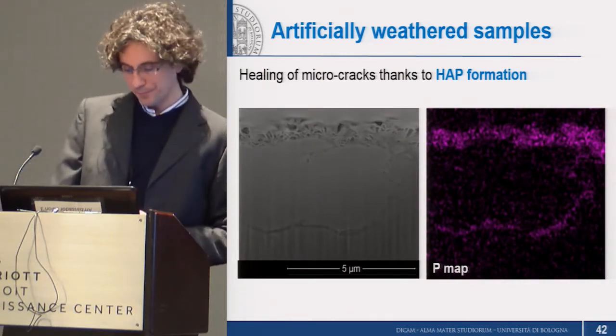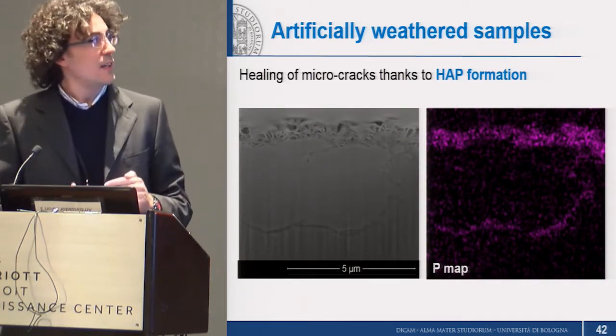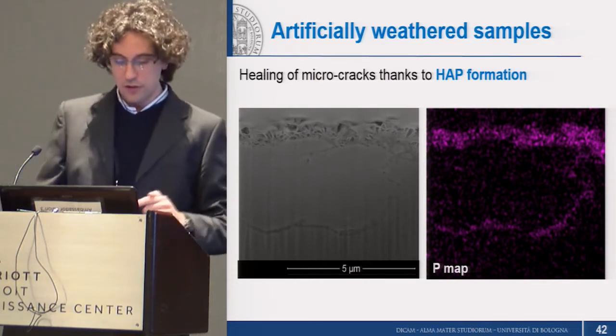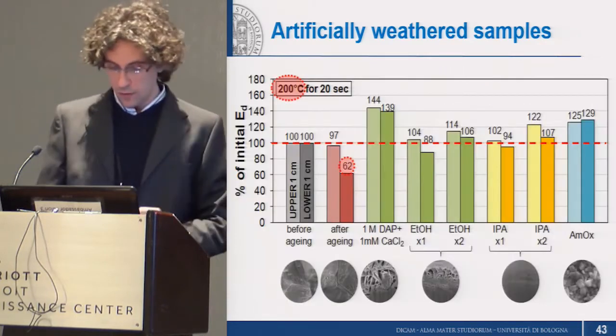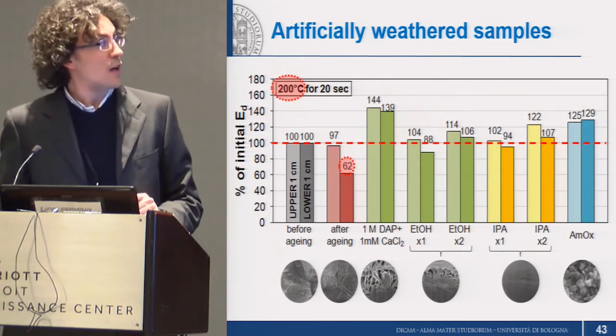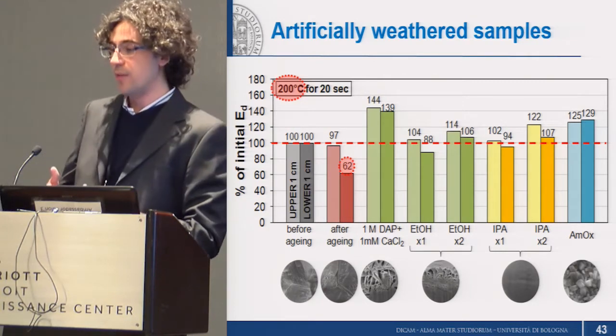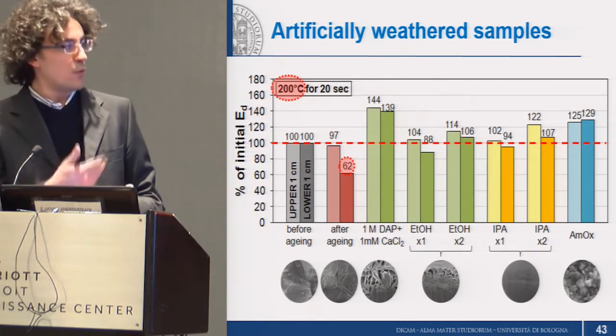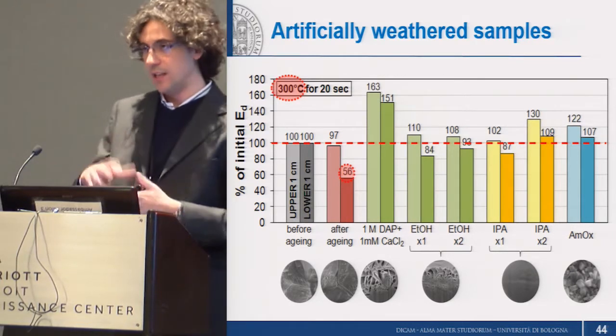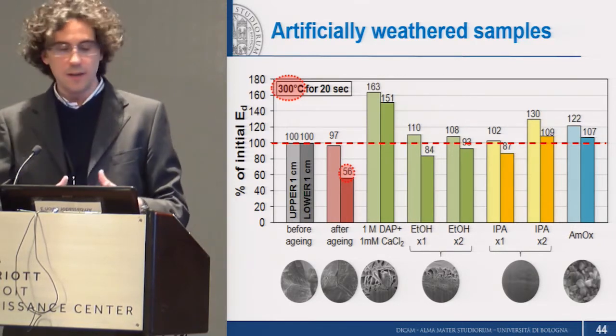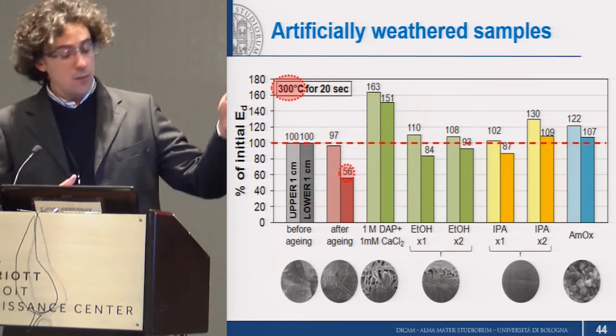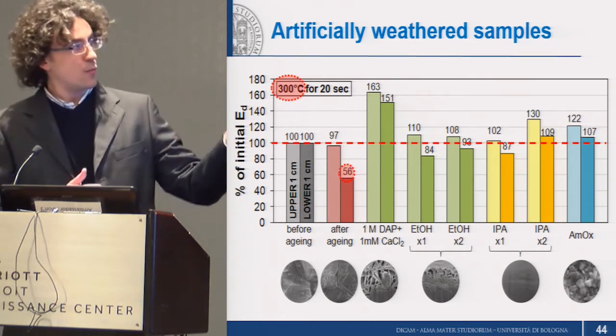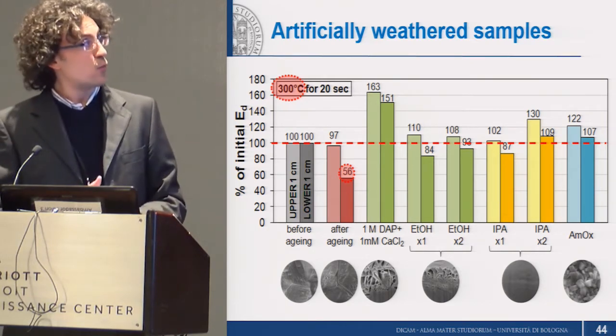So then we investigated different levels of deterioration, by heating, for instance, at 300 degrees rather than 200. So in this case, we reached a more significant level of decay, meaning more cracks with bigger size. And then we compared our treatments, again, with commercial treatments and different formulations.